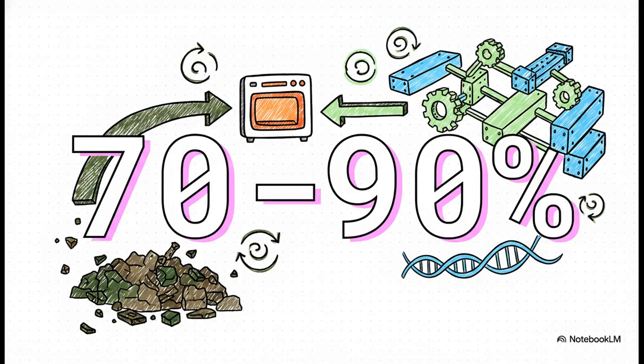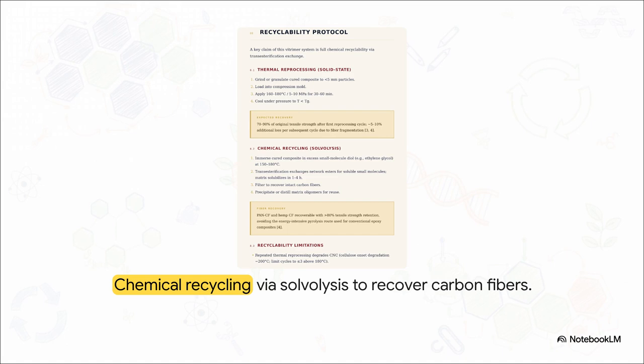And the result of that straightforward process? It is absolutely astounding. You recover 70 to 90% of the material's original tensile strength after the very first thermal reprocessing cycle. You've taken what would normally be permanent, unrecyclable landfill waste and molded it directly into a brand new, high-strength structural part. But what if you need those pure, pristine, intact carbon fibers back?